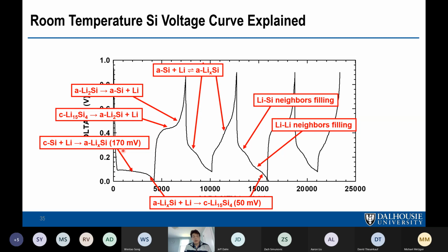electrochemistry of silicon. So at about 170 millivolts, crystalline silicon is lithiated in a two-phase region. The two-phase region is between crystalline silicon and lithiated amorphous silicon. If you go below 50 millivolts, the amorphous lithiated silicon crystallizes to the 15-4 phase. The delithiation of the 15-4 phase happens in a two-phase region, again producing amorphous lithiated silicon, and eventually producing amorphous silicon when it's fully delithiated. When you lithiate amorphous silicon, it's in a single-phase region, and if you stay above 50 millivolts where this phase forms, you can cycle silicon in a completely single-phase region.